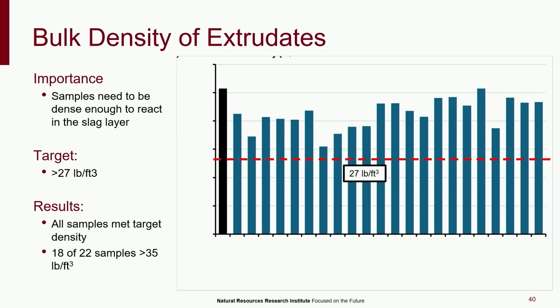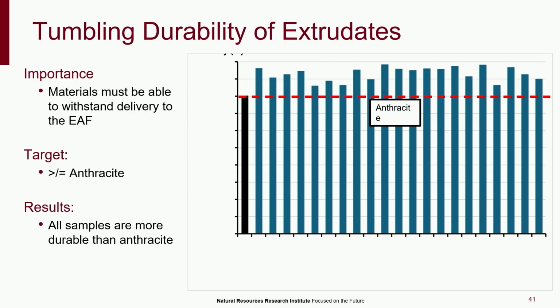We also had some density and durability requirements from our industry partner, which they gave us. It needs to be at least greater than 27 pounds per cubic foot. In black here we have, I'm surprised our units on my graphs are not here. Sorry, there must have been some weird conversion with my presentation. But so the black is anthracite, and then the rest of all our formulations. All of them surpass 27 pounds per cubic foot, and then some of them are getting close to that anthracite density. We also did tumbling durability. We needed to be greater than or equal to anthracite, and all of our samples actually exceeded that.